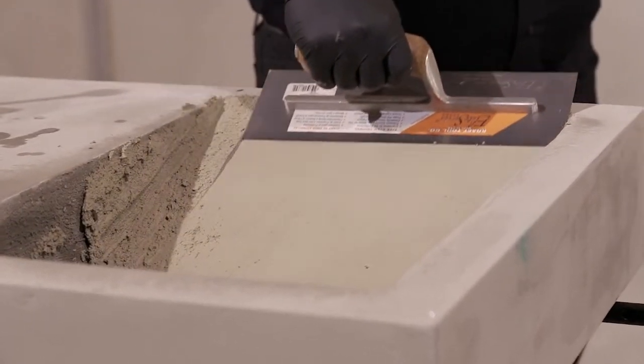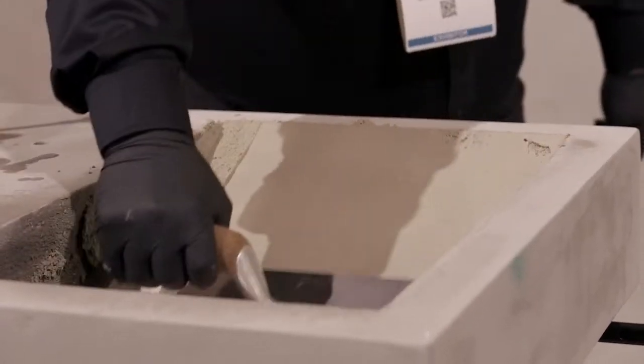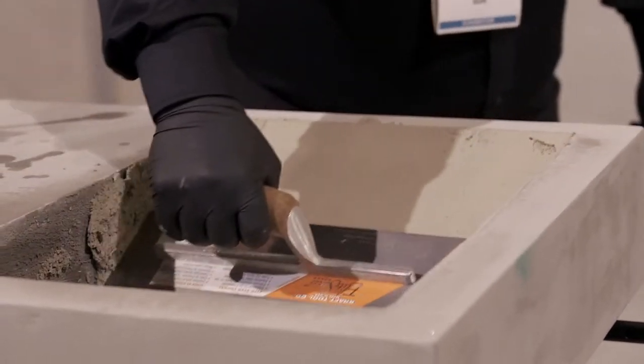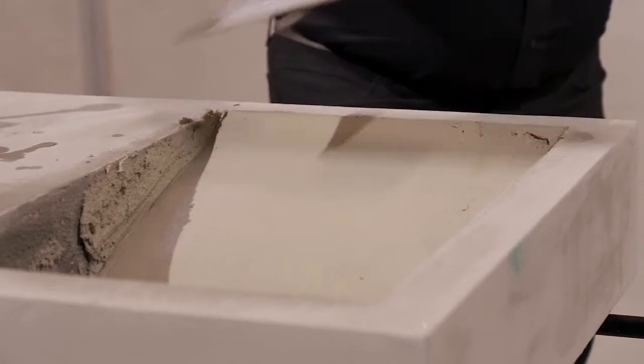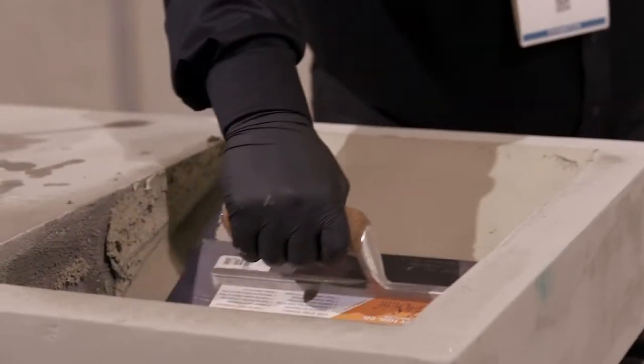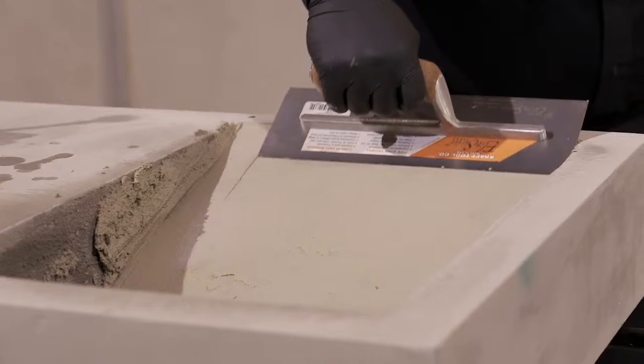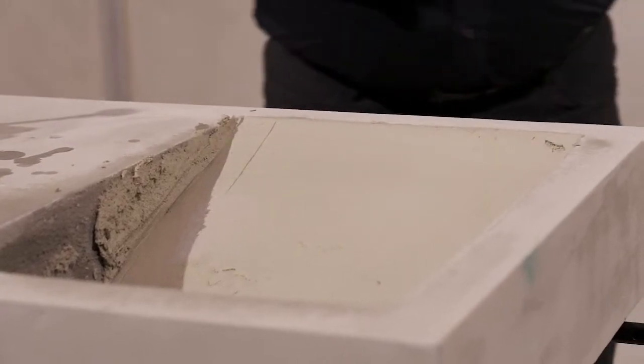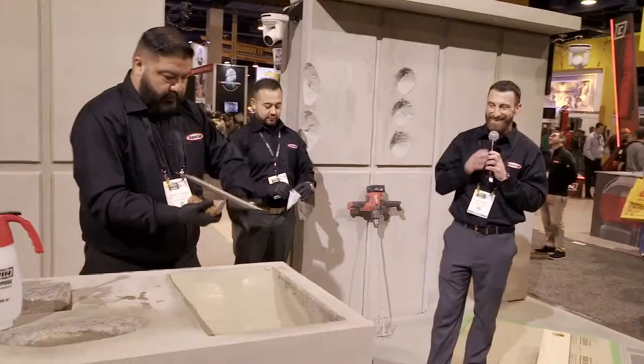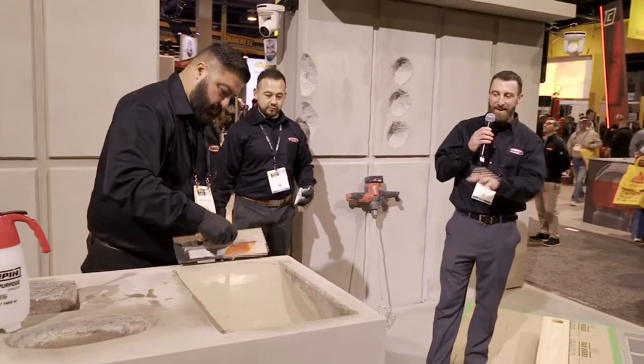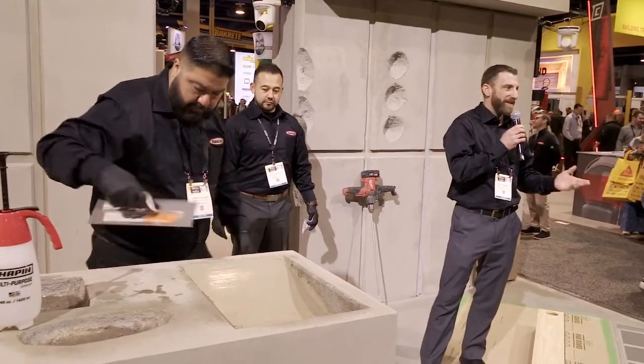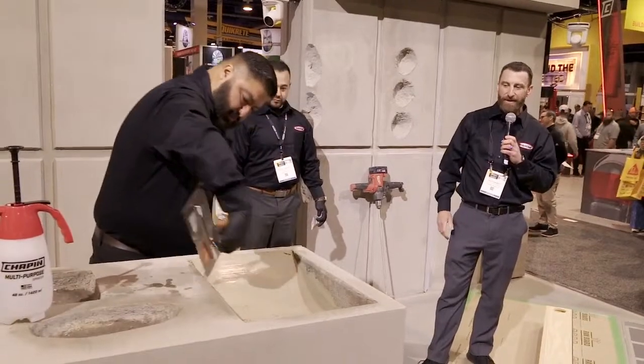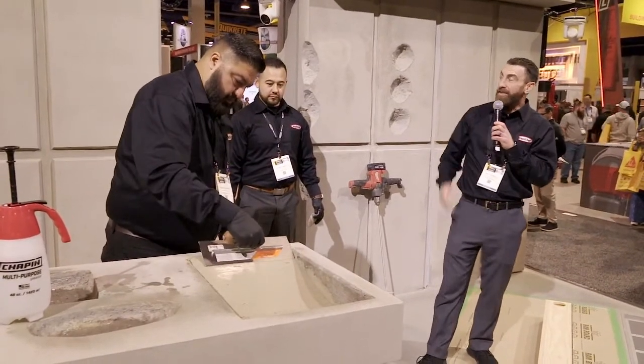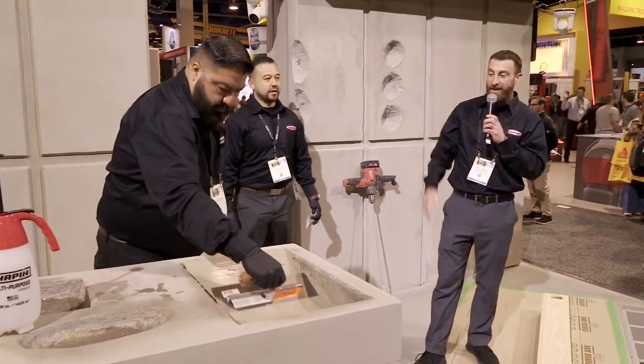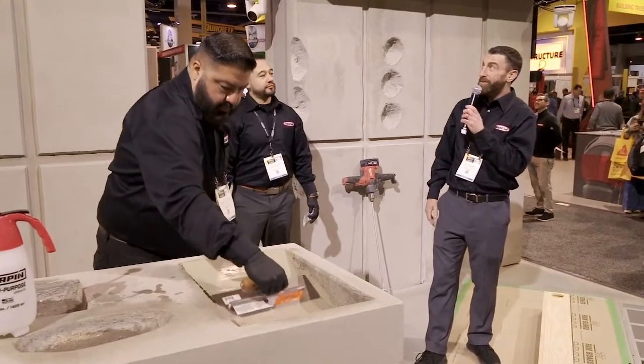This product has about 10 minutes of working time, so we definitely want to make sure that all of our personnel and our equipment are ready to go before we even start mixing. We've had people who are unprepared, who lose their equipment because the material kicks off way too fast. But the benefit of that, 10 minutes of working time, we're actually getting structural strength in just 1 hour. This product can gain 3,000 PSI in 1 hour and will exceed 9,000 PSI in 28 days.